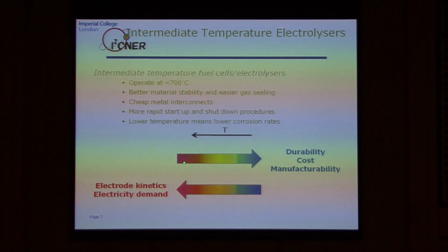Low temperature always means lower corrosion rates. So these are the things that improve as we go down in temperature: durability, cost, and manufacturability. But unfortunately, at high temperature the electrodes work much better - electrode kinetics are faster, and we reduce the electricity demand. So what we need is a temperature range, a sweet spot where electrolyzers work efficiently, durably, and cost effectively. I believe this optimum range is between 700 and 500 degrees centigrade.